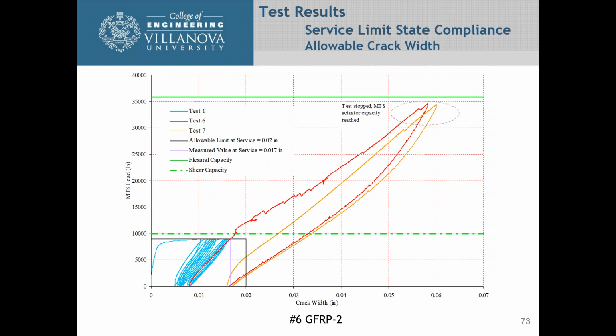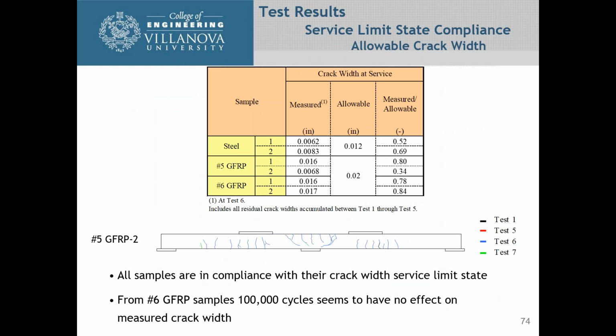Taking a look here for the second sample for the number 6, you can see again that the requirement had to be less than 0.02 inches for GFRP, and our measured value is 0.017. So looking at everything, if you look at the ratios of measured versus allowable, you want all those to be less than 1, and you can see for the steel, we were less than 1, meaning that we are less than the allowable, and for the GFRP, we were in compliance with the service limit state crack widths.